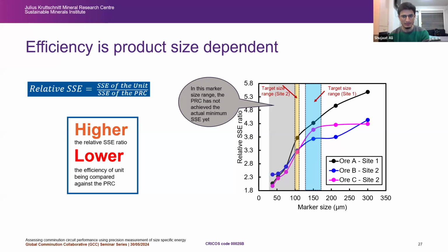I think in my work, I kept it 0.8, and there was a reason behind that. The reason was that was the very reduction ratio where I was achieving just that little fracture that I wanted. And how did I basically set that reduction ratio? I basically validated that reduction ratio against the device called short impact load cell. I broke the same ore type on short impact load cell that gives you primary fracture energy.